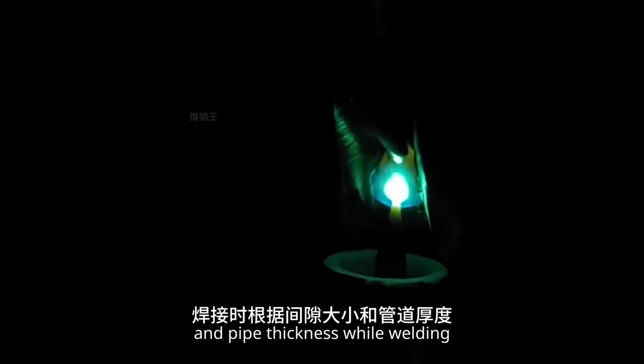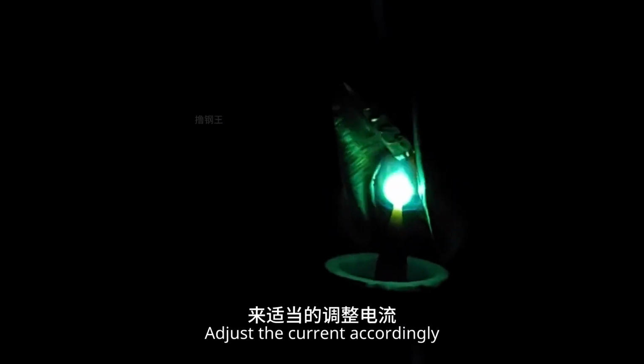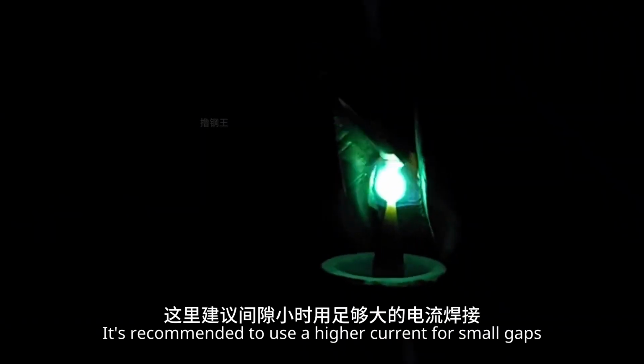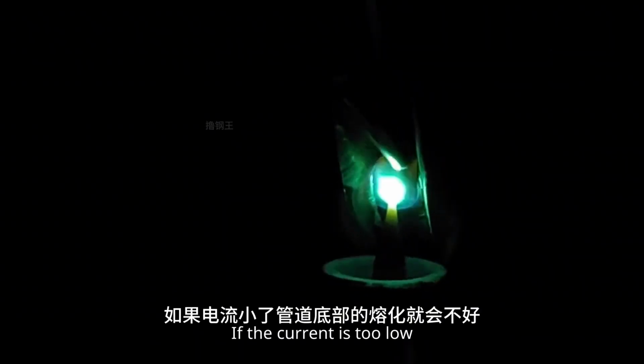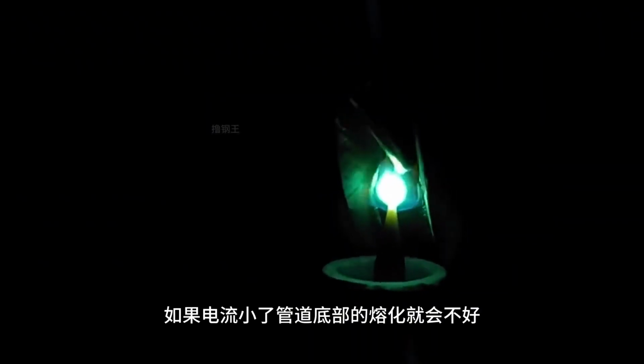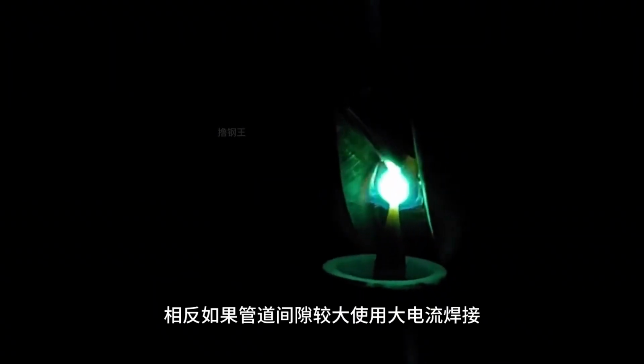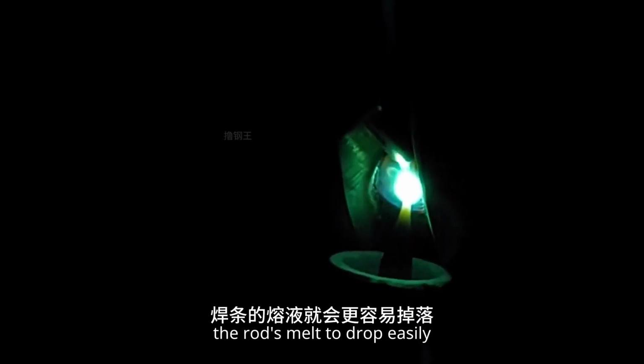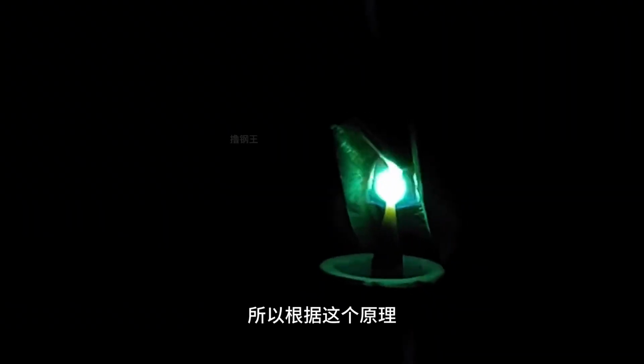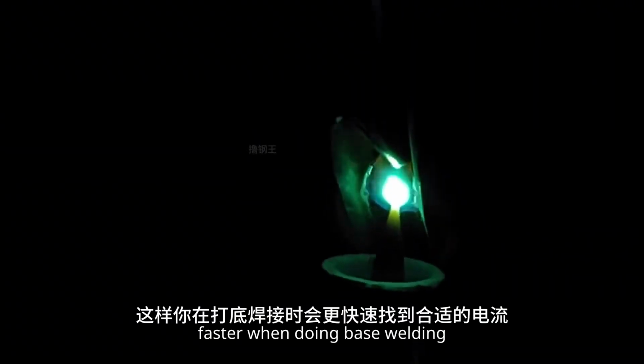Adjust according to the gap and pipe thickness while welding. Adjust the current accordingly. It's recommended to use a higher current for small gaps. If the current is too low, melting at the pipe's bottom won't be good. Conversely, for larger gaps, using a high current can cause the rod's melt to drop easily. Based on this principle, the current we are using for welding is 110. Remember this principle, so you'll find the right current faster when doing base welding.